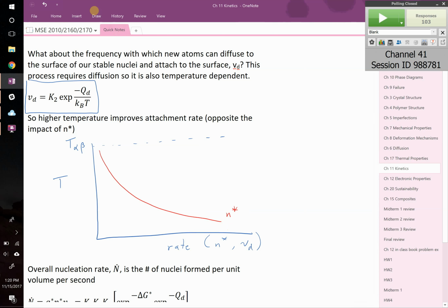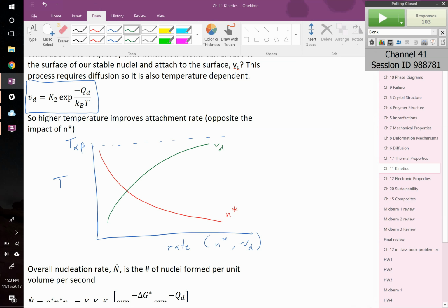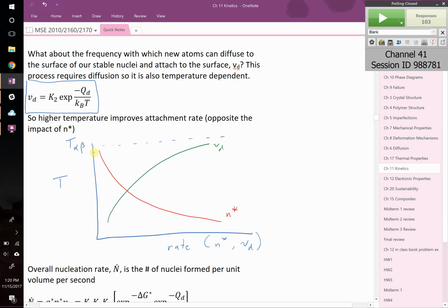I'm going to pick a different color, we'll do gray. V sub D, right there, that increases with temperature. It's a thermally activated process, right? So you've got these two things in competition with one another. And since you have to have both of them, we're going to multiply those two terms. And we're going to see that the overall rate of transformation does something like that. We'll call that N dot, is how they normally write it. So basically by multiplying the formation of nuclei and the growth of those nuclei, you get the overall transformation rate.